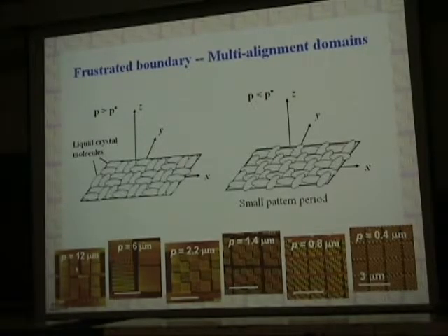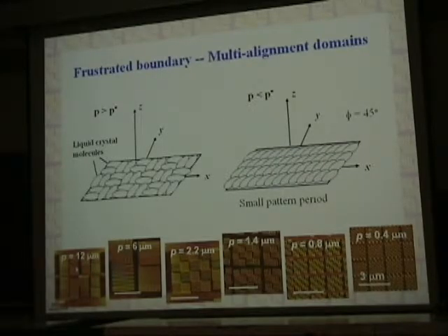However, the wigglings correspond to deformation in the liquid crystal director field, and that leads to elastic energy. Imagine now you decrease the pattern period, that elastic energy is going to increase. And at some point, the energy will be so large that the liquid crystal would rather relax into a uniform configuration, which by symmetry of this pattern should be along the 45-degree azimuthal alignment.